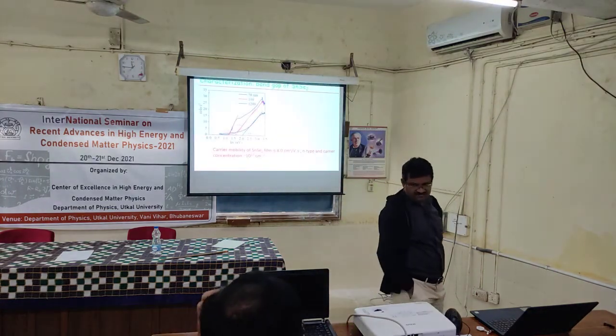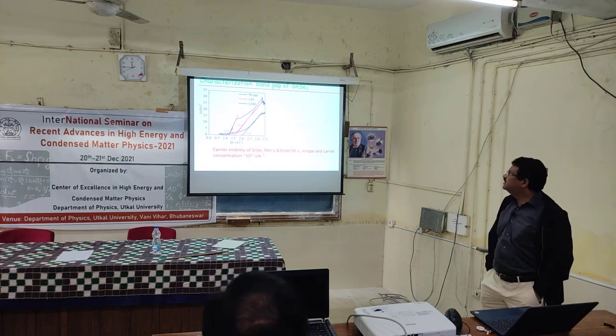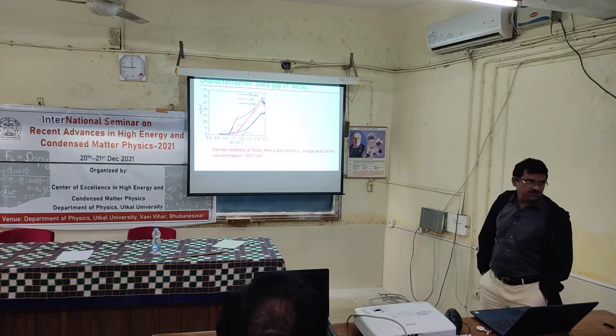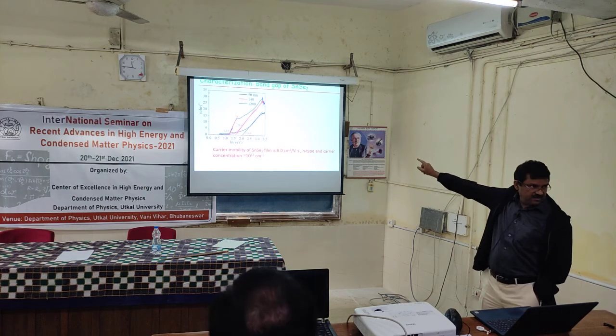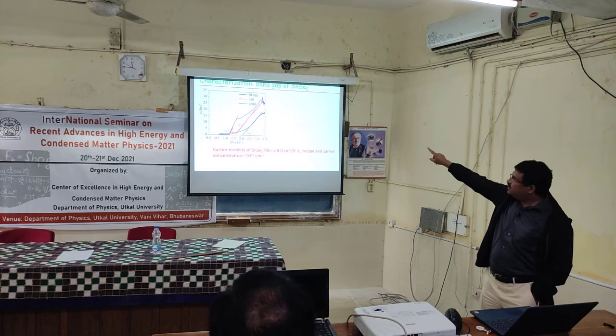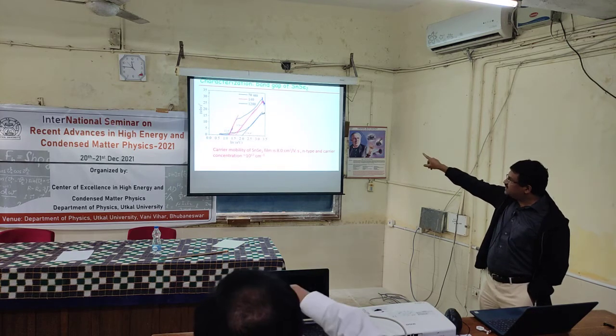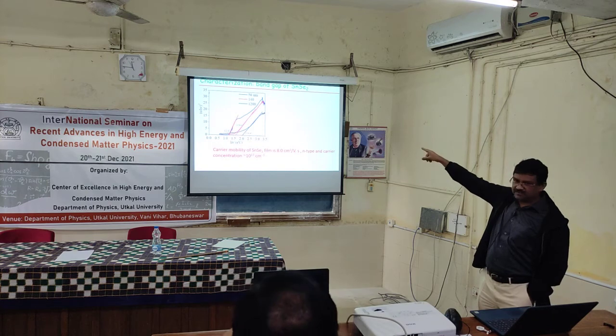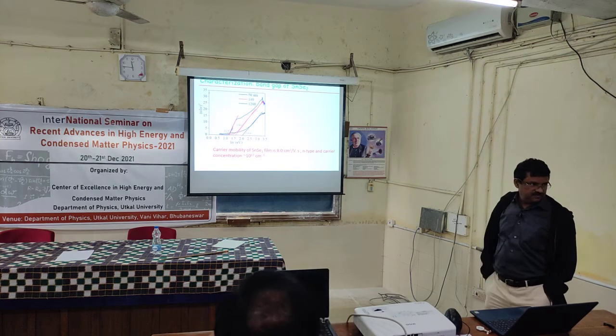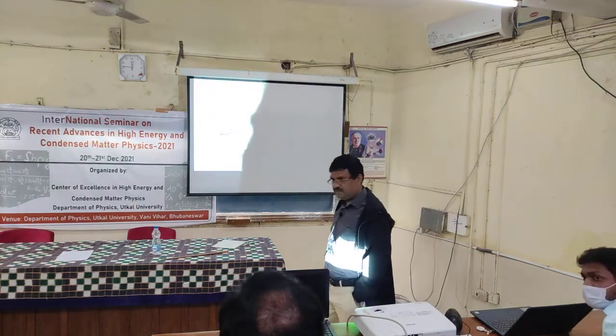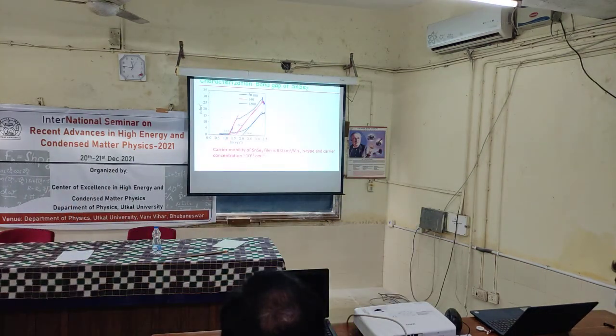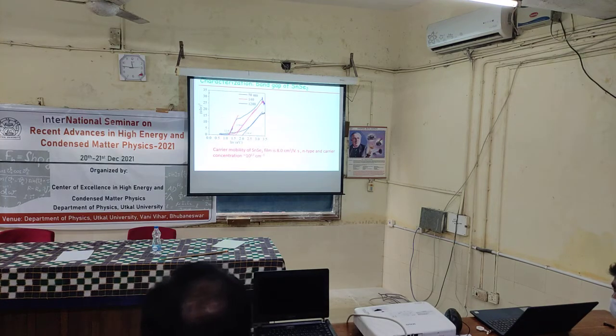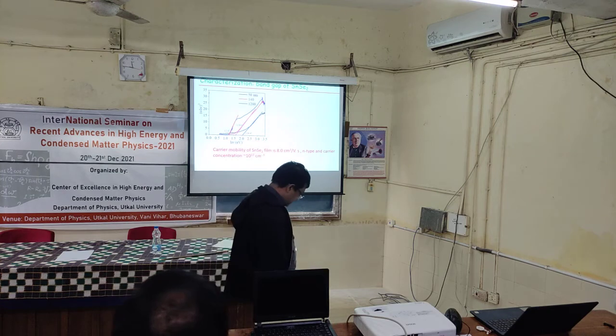That's basically the right approach actually, if you are a beginner. In the top one you can do a maximum there also. Upper side, the slope will be low. And you cannot have two bandgaps. So you are interested in the proportional resistance. If it is not linear, you can take the y-axis divided by the x-axis and see where the maximum is. Then you can take that as a bandgap. So you calculate that arithmetically or just observe it.